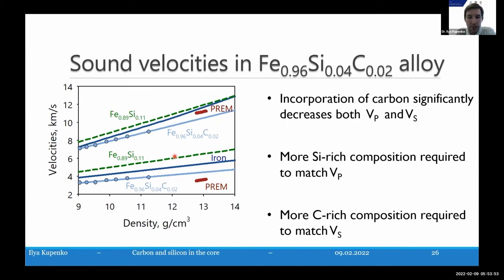So even with a very small amount of carbon, if we heat at least below 100 GPa, we always form carbide. Not form carbide, but it always decomposes to carbide. So the carbon doesn't stay inside the structure. And so we were not able to determine the temperature effect, because we cannot discriminate between the two samples. We measure an average between carbide and alloy with inelastic scattering.